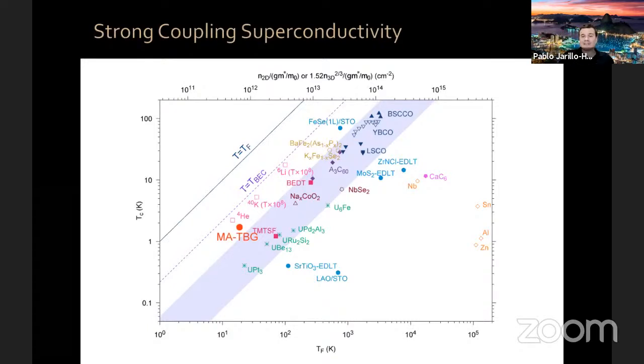We don't have any evidence yet of what's the order parameter for the superconductivity, okay? We do not know. Of course, condensed matter physics is not a democracy, but let me just say, maybe about 10% of the theorists think it's electron-phonon, 90% think it's interaction driven, okay? Electron-electron interaction driven. But of course, that doesn't mean that it cannot be electron-phonon, okay? What I will say is that you mentioned the importance of this high density of states, but the data point I can add is that in the region where the density of states is the highest, superconductivity is not there.